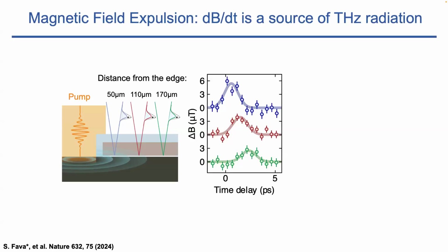We have a question. Characterizing HC1 of your samples, and then doing the experiments far below it. Yeah, so the point is that HC1 along the C-axis of the cuprates is a very small number, a few millitesla, and then the signal is small enough that we just need to get Q. We sort of do the experiments at HC1. If you go far below HC1, then the noise is such that we would be having a different conversation.